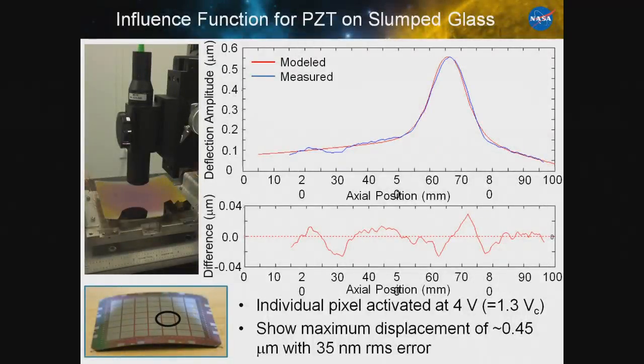And so the previous figure was an example of a flat glass segment where we had piezoelectric coated on the thin glass with an array of piezoelectric cells on it. One of our next jobs was to do comparable depositions onto slumped glass optics. So you can see here a pre-slumped glass optic. It's about a 220 millimeter radius of curvature, so appropriate for one of the next generation space telescopes. We deposited on, so this is basically the backside. So this is where the actuators are.